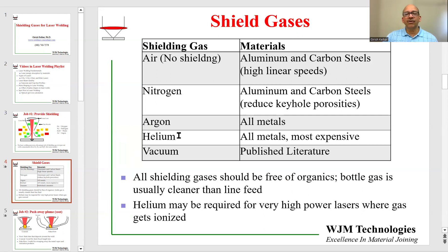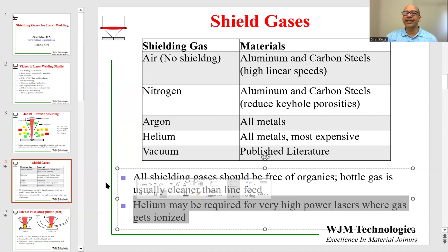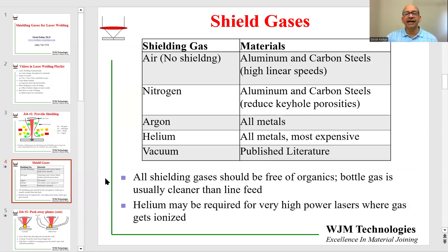Helium is the other inert gas which can also often be used, but it is first of all very expensive, and secondly it is very light. So you have to provide a lot of shielding gas to have good coverage over the molten metal when you use helium — that's why helium is not as commonly used in laser welding as in arc welding. However, if you are making welds with a very high energy density beam, especially with new fiber lasers with single-mode laser light, there might be situations where argon is getting ionized during welding. In that case, you may have to switch to helium to avoid the shielding gas from getting ionized.